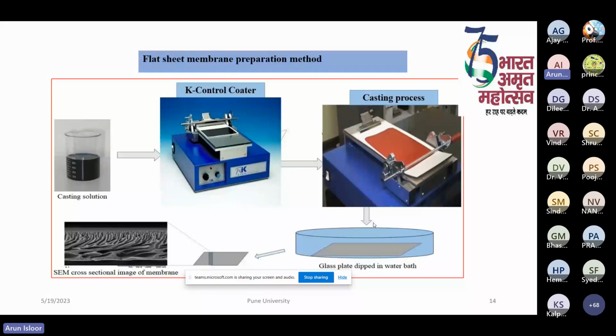The procedure is very simple. First, prepare the polymer solution as per the required viscosity, and then introduce it on the glass plate, which is mounted on this automated instrument. The polymer solution can be uniformly spread across the glass plate with the automated moving doctor's blade. After that, remove the glass plate and immerse it in a container containing distilled water. Within a few minutes, the separation of the polymeric membrane will take place.